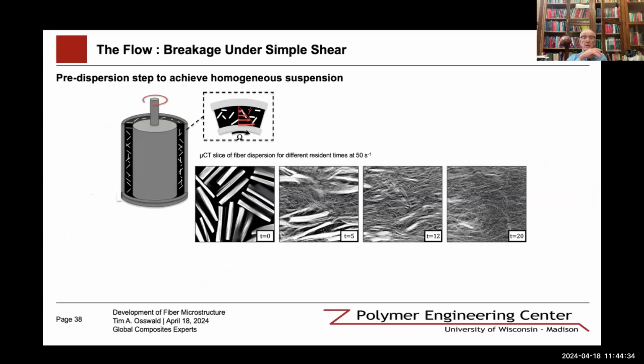And so that brings me to the final part. There is an effect that hasn't been included, and that is the dispersion of the fibers. So if we look at the flow in the fiber breakage experiment during the Couette flow experiments, and do micro CTs at different times,